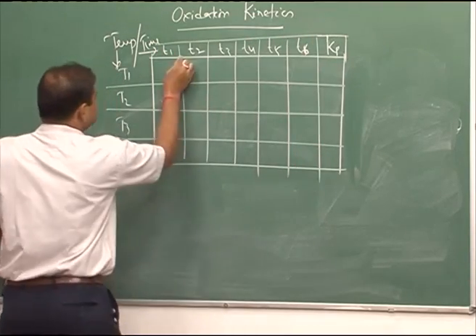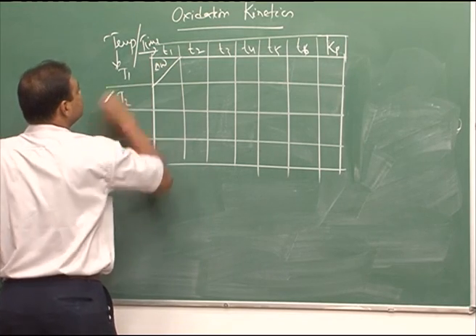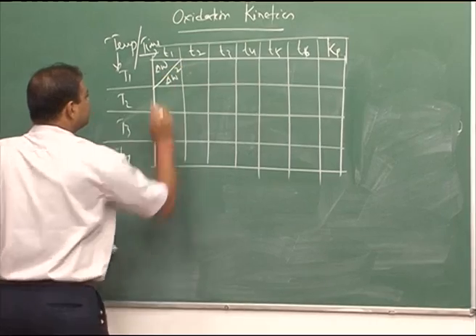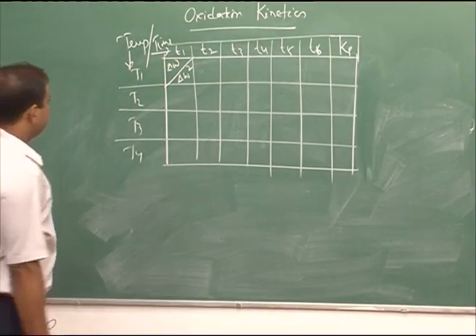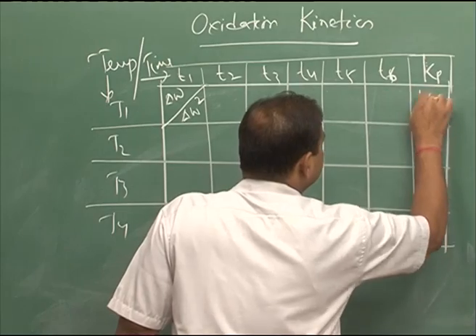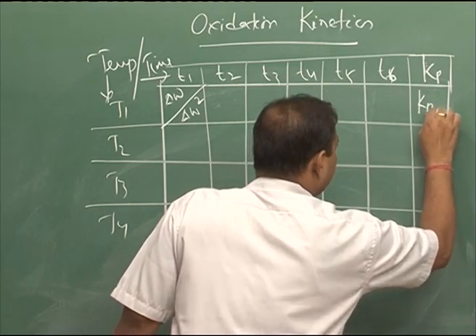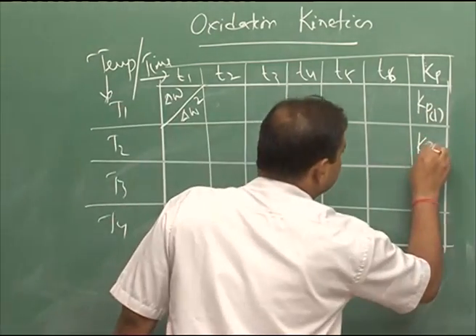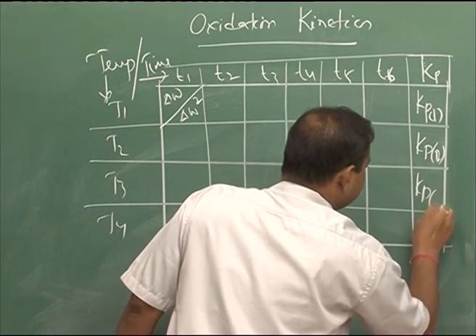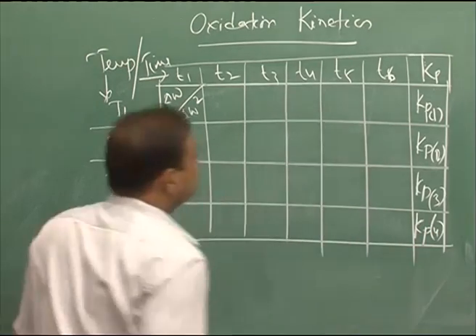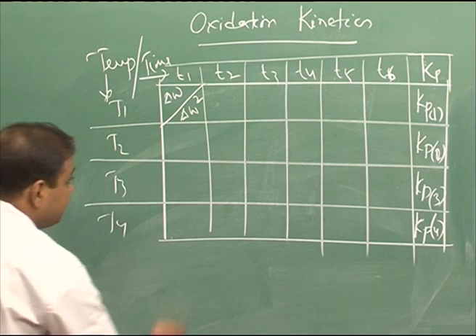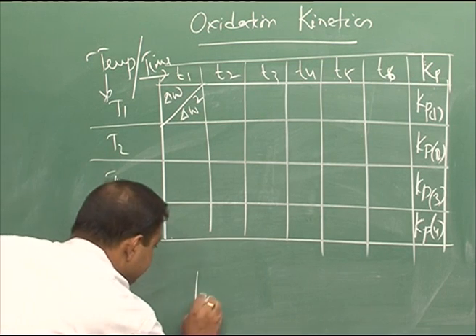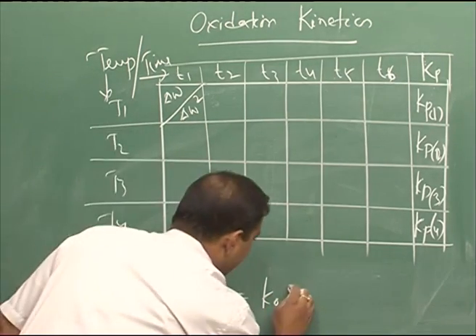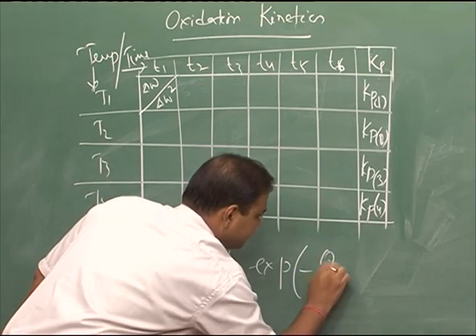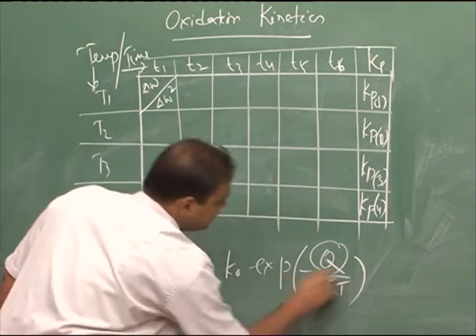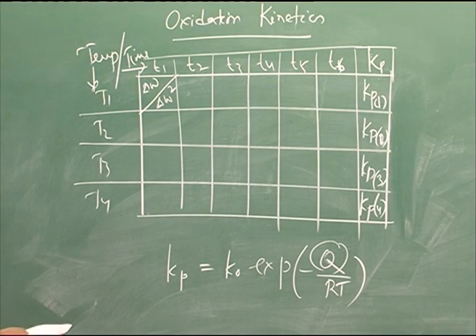This table, if we make, then let us say the upper half part is del W, and the lower half, if we plot del W square, like this, if we continue like this, then we can also find out the value of K P. We can plot K P 1, which is at T 1, K P 2, K P 3, K P 4. So we get all the values of K P at different temperatures, and since it is a thermally activated process, we can relate K P via the Arrhenius equation, exponential minus Q by R T, where Q is the activation energy for the oxidation process.